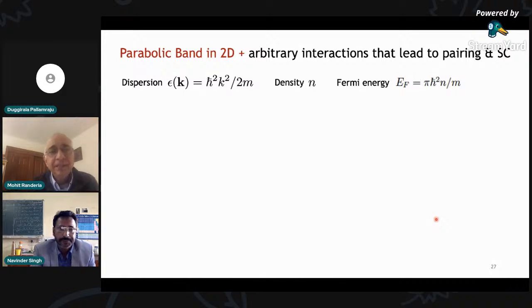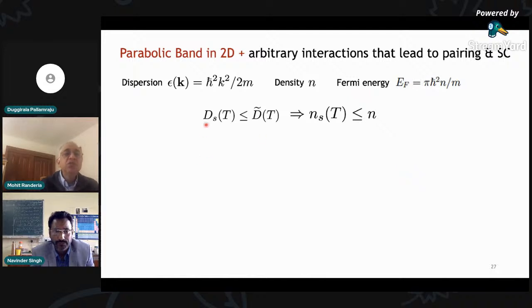As with anything, always look at the simplest case first. So how about looking at a parabolic band with a dispersion k squared over 2m, okay? And put in whatever interactions you want that lead to superconductivity and pairing. What results do we get? We have a dispersion, a density of particles, a Fermi energy, and whatever interactions you want. The first bound, that the superfluid stiffness is bounded by the optical spectral weight, just reduces, in this particular case, to the statement that the superfluid density is less than the total density, which is very natural. How can it not be?